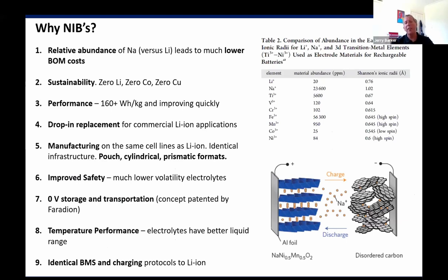Why sodium-ion batteries, right? Well, some of these things are fairly obvious, some maybe not so obvious, but the relative abundance of sodium just means that we can have a much lower bill of materials than corresponding lithium-ion chemistry. Sustainability: when we started out in 2011, I always used to say, look, we're the sodium-ion company, we're the zero lithium company. But actually, as we move forward, we concentrate more on the fact that not just are we zero lithium, but we're zero cobalt and we're zero copper, which is very important, right? Why we're zero copper, as you probably understand, copper is the current collector for the negative electrode in lithium-ion batteries. And because of the chemistry of sodium-ion, we use aluminium current collectors on both sides of the cell. So that's a useful cost and weight advantage over corresponding lithium-ion.